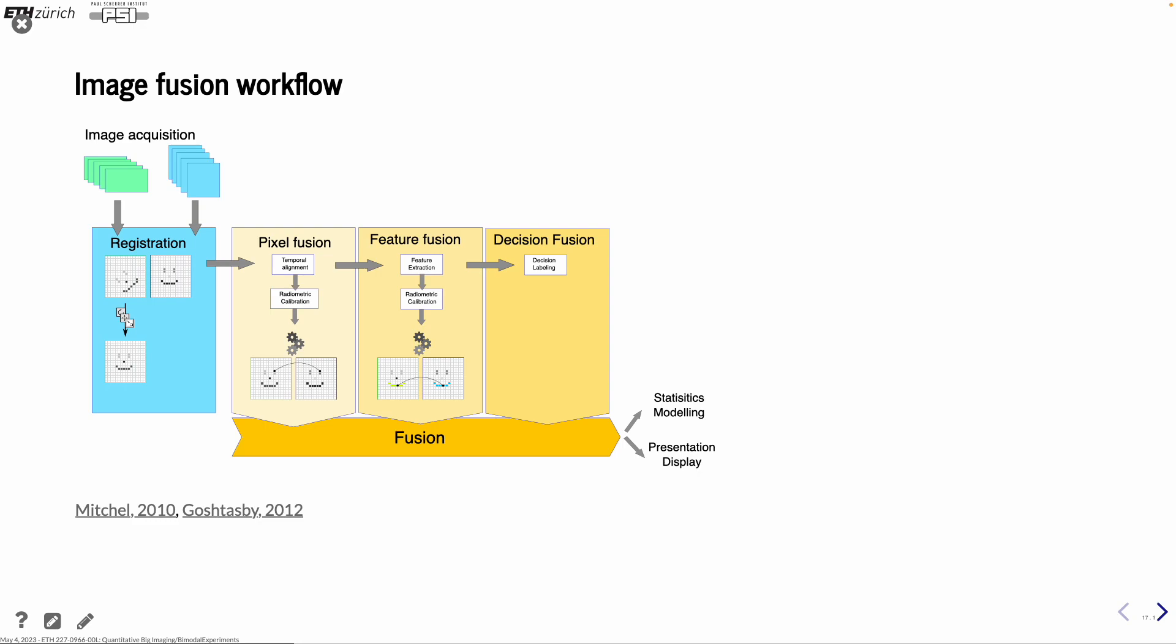And a little bit more graphical overview of this is the workflow you have for the fusion. And the first step is, of course, getting your images. And the images are most likely not aligned. So the first step is that you have to do the registration that we talked about last week. So in principle, just getting the images on the same grid and rotate them in the same way that they are matching up. Once you have done that, you can go on doing the pixel fusion, may need to do some further alignment, and the calibration to get the gray levels on the same scale. And then you can compare pixel by pixel. You could also go on then to the feature fusion, where you first extract your features, and then do some, again, some calibration to get the levels on the same scale. And then you compare different regions that should be comparable, or items that are comparable, and try to fuse those.